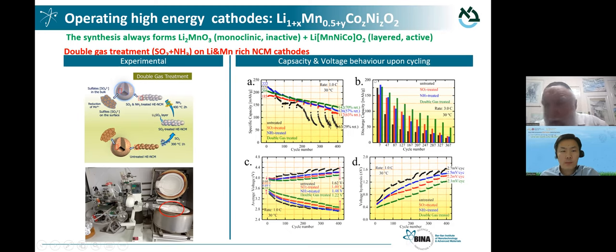a nice response. So here, for instance, look at the discharge. These charts show experiments in which we change the rates throughout the experiments. This one, the green, reflects our favorite, which is the double gas. The blue and the red are only one gas treatment, and then the black is the reference untreated material. So we can see the capacity fading, which is pronounced and expected. There is also an issue of voltage fading, voltage hysteresis, which increases, and also the average voltage for discharge also decays during cycles.